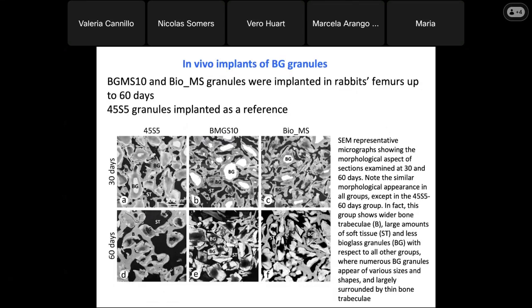So here you see the implants of bioactive glass granules. Such granules, both of BGMS10 and BioMS, were implanted in rabbits, so in rabbits' femur, up to 60 days. And 45S5 granules were implanted as well as a reference. Here you can see the SEM, scanning electron microscopy, images of 45S5, BGMS10 and BioMS after 30 days and 60 days, where you can see the bioactive glass granules, but also the bone trabeculae and the soft tissue.